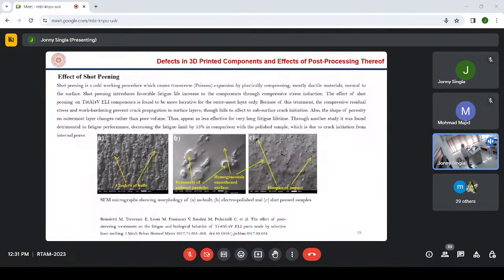Because of this treatment, compressive residual stress and work hardening prevent crack propagation in the surface layer, though it fails to affect the subsurface crack initiation. It is only a surface treatment. It is not going to affect the bulk core of the material, right? Also, the shape of porosity on the outermost layer changes rather than the pore volume, right? Thus it appears less effective for very long fatigue lifetime.